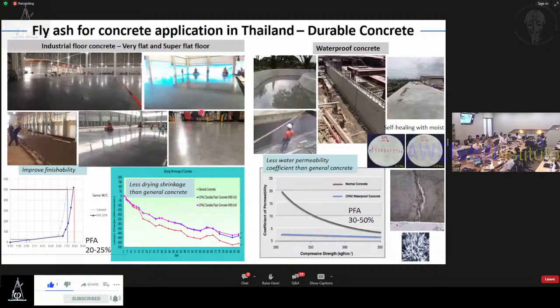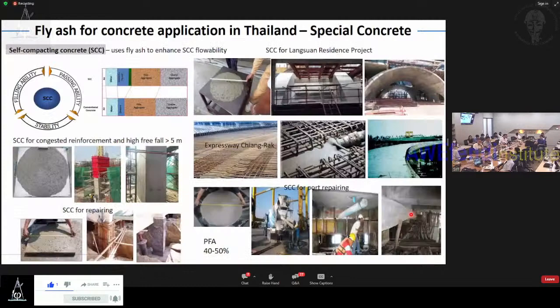Also, as I mentioned, for waterproof concrete, we found some effect from fly ash: when the concrete cracks and is exposed to some moist environment, after that it can heal itself when moisture comes to the structure. So it's an effect of fly ash as well. So this one just wants to show you what applications we use. And self-compacting concrete is used a lot in Thailand right now.